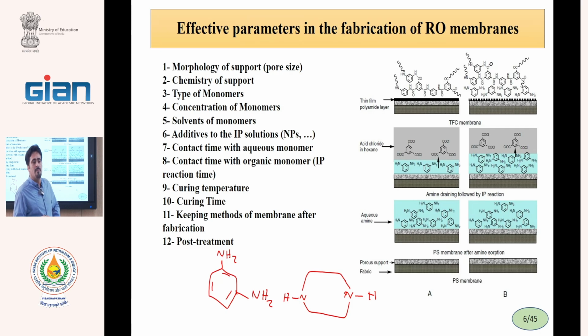The flux of RO membranes is related to the thickness of this thin film. Some factories prepare this layer 200 nanometers, other factories 100 nanometers. And in this case, flux increases 50%. Therefore, we try to reduce the thickness of this layer, but we must prepare a defect-free layer. With reducing of the thickness, the possibility of defects increases. Therefore, if we can prepare a thin film layer without defects, we have a good process.